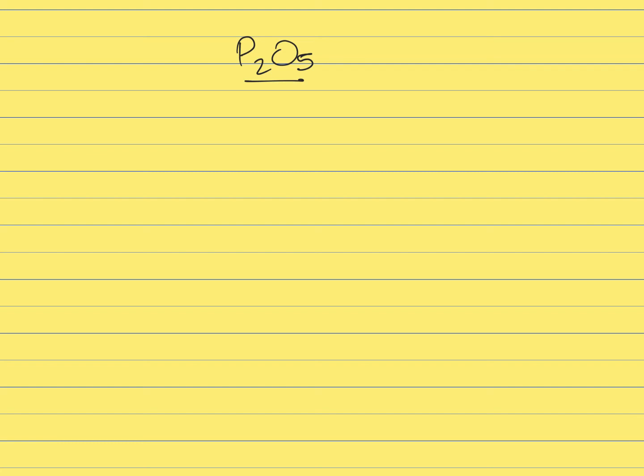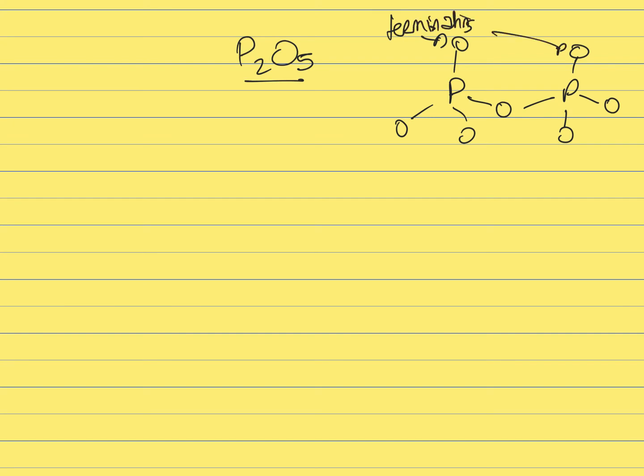So in this case, as a reminder, the structure of P2O5 is that the phosphorus atoms are 4-fold coordinated. And in contrast with SiO2, in the case of the P2O5 glasses, around each phosphorus atom, there is one oxygen that is a terminating oxygen, an oxygen that is not connected to any other phosphorus, while the 3 others are bridging oxygen. They are connected to another phosphorus atom. So that's the basic structure of P2O5.